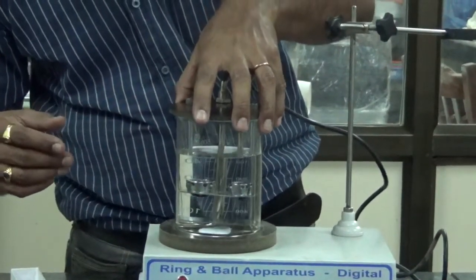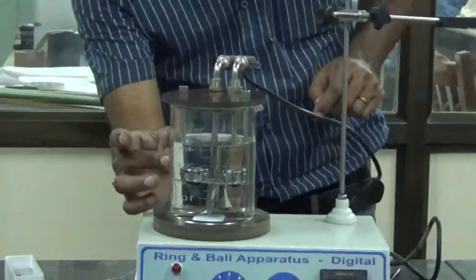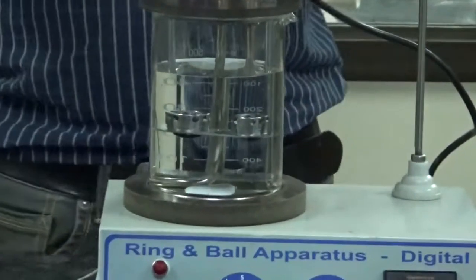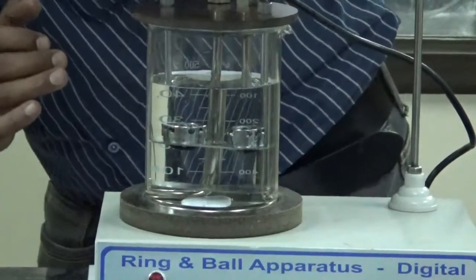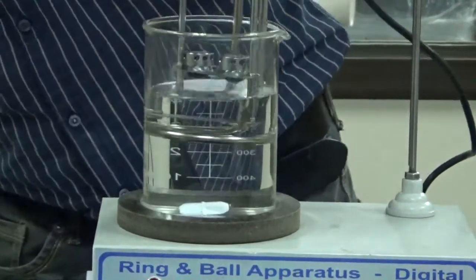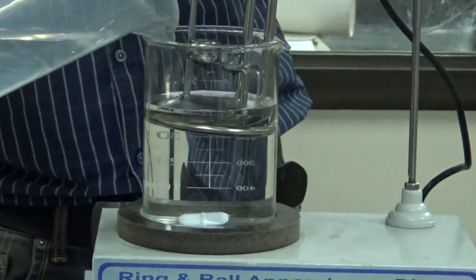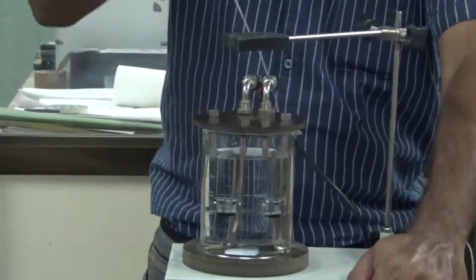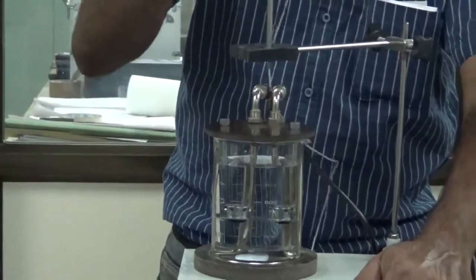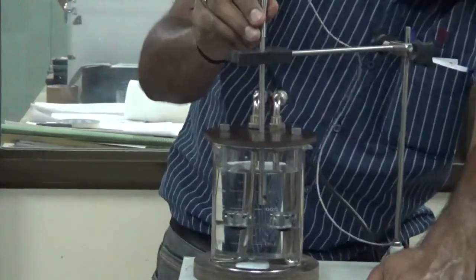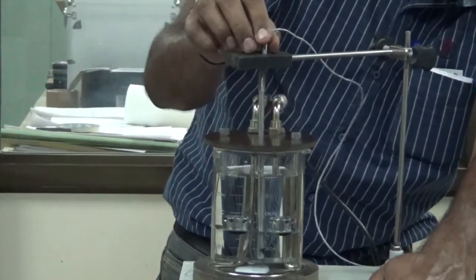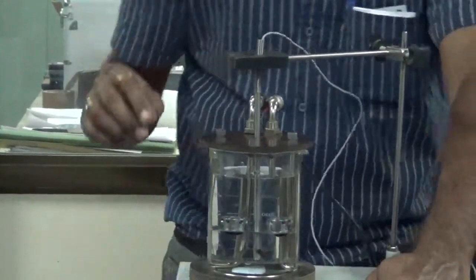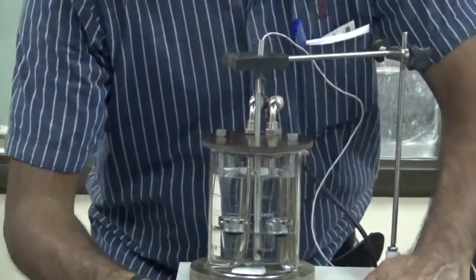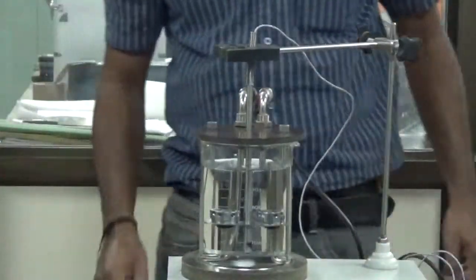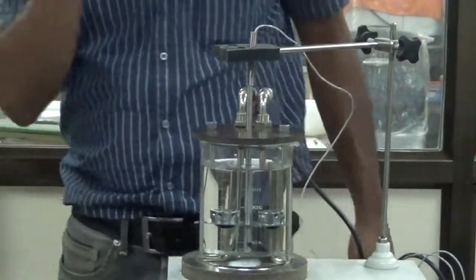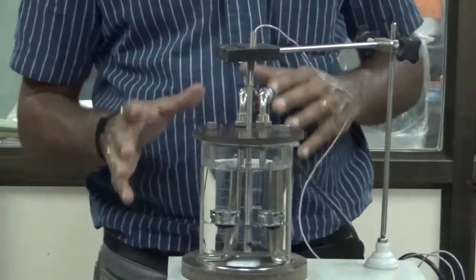As I told you, above the sample the water level should be at least 50 mm. Right now it is not, so I will fill more. Now I am going to place this digital thermometer inside the water so that we can measure the temperature. Then I have adjusted my heating rate to 5 degree per minute. The heater is started, the magnetic stirrer is started.